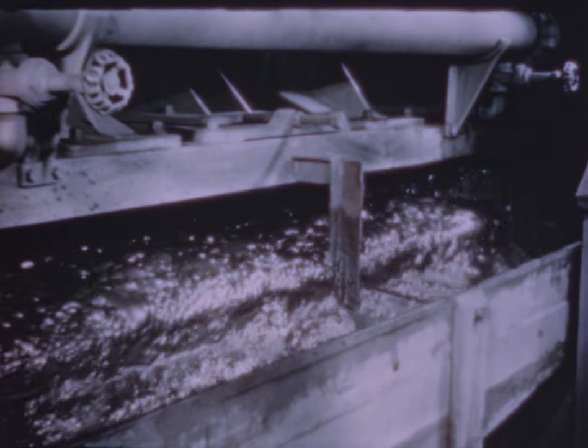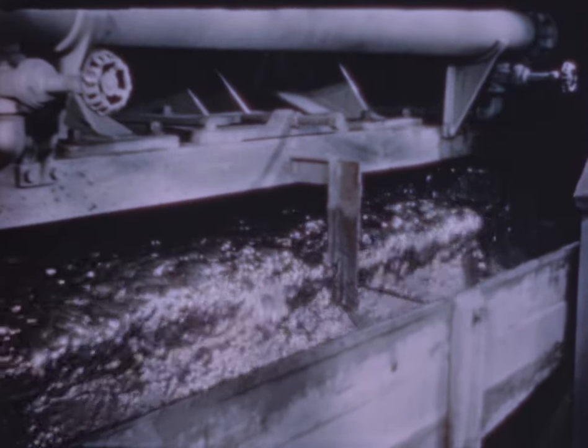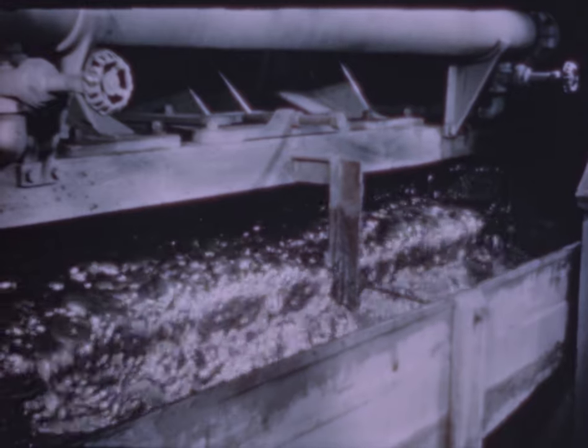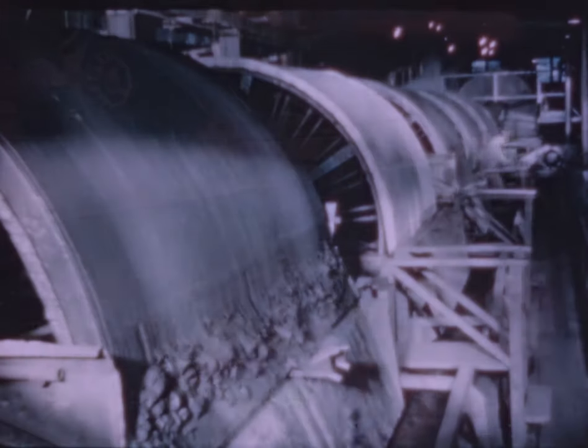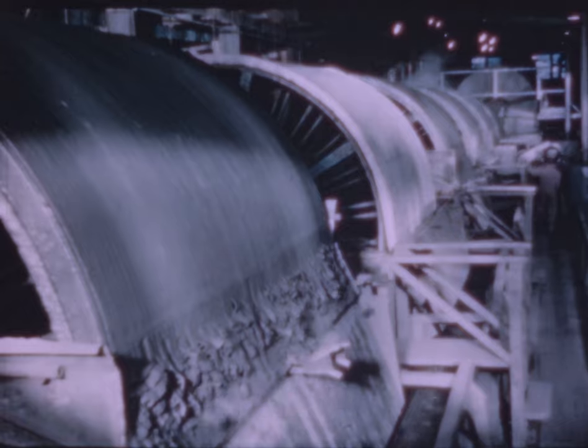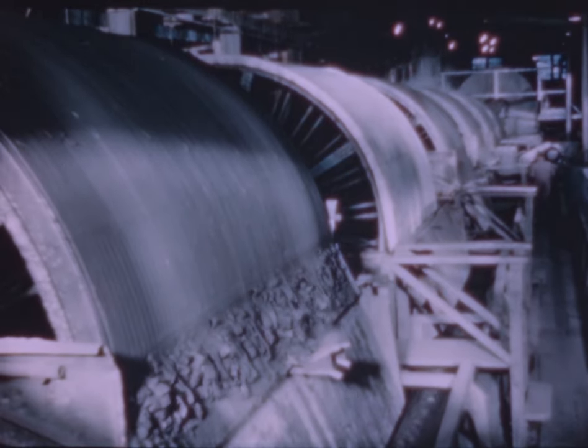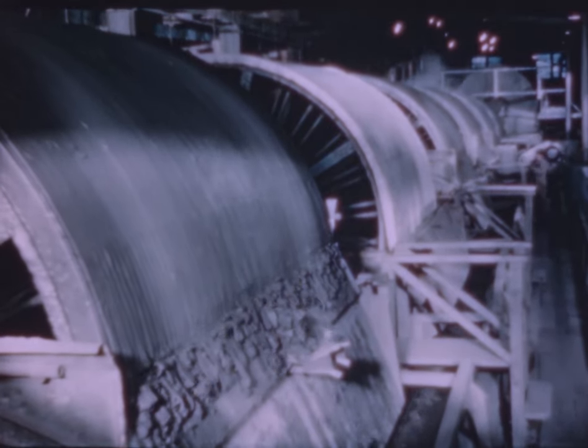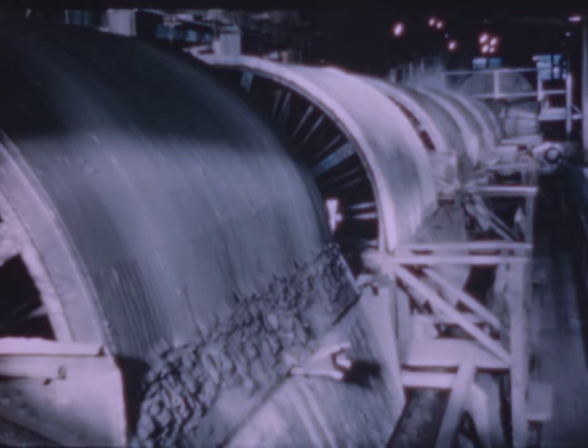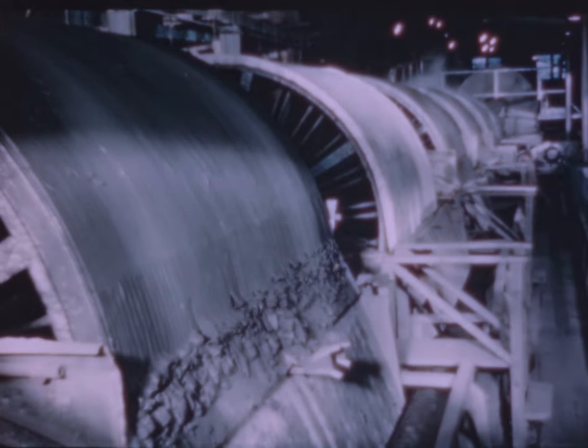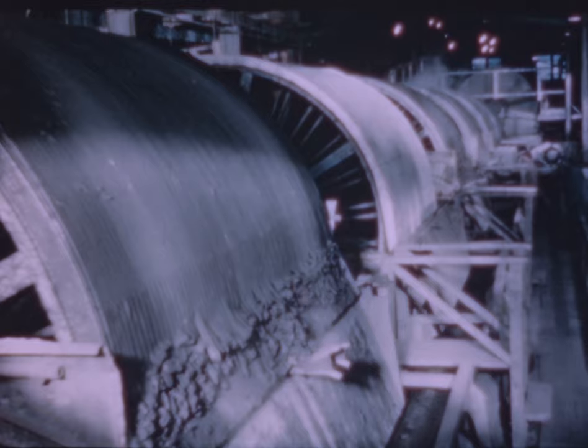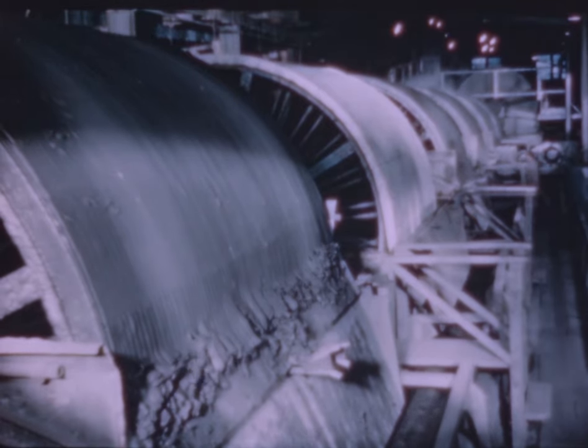The overflow, or froth, is too wet to be handled in the roasting furnace. So after partial dewatering in settling tanks, the water content of this heavy, mud-like sulfide mass is further reduced in these filters. A partial vacuum inside the canvas-covered discs draws the water out of the cake. The concentrate now contains about 25% copper and is ready for the next operation, roasting.